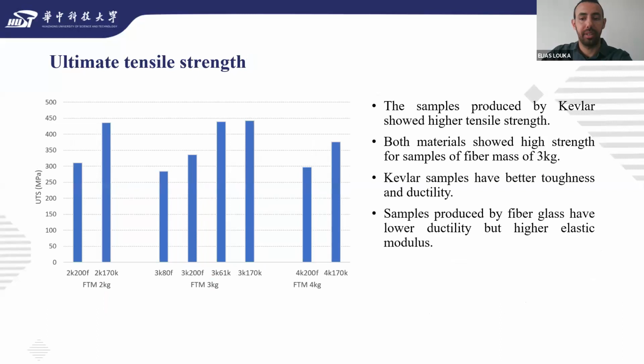In this figure, we can see the ultimate tensile strength per fiber total mass. The samples produced by Kevlar showed higher tensile strength compared to those produced by fiberglass. Now, if we compare the different masses, we will see that samples of fiber mass of 3 kilo show the higher tensile strength for both materials, fiberglass and Kevlar. It can also be observed that Kevlar samples have better toughness and ductility than the samples produced by fiberglass. On the other hand, fiberglass samples have lower ductility, but they have higher elastic modulus in most of the cases.